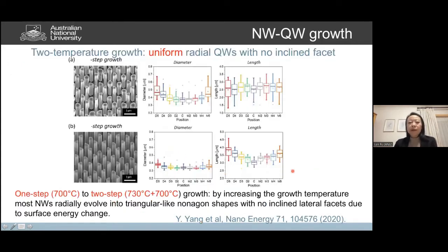So a student, Sook, has come up with a new idea to introduce two-temperature growth. By reducing the growth temperature in the first step, he wants to change the energy during the nanowire growth, and thereby enhance the uniformity of the nanowire. This is one-step growth, and this is two-step growth. You can see that by using this two-step growth, he's able to modify the shape of the nanowires and improve the uniformity significantly, both in diameter as well as length, and introduce a very nice triangular shaped nanowire across the whole nanowire length. This is because of the surface energy change by the modified growth temperature.